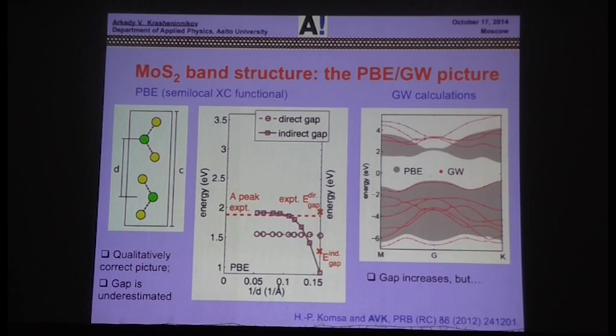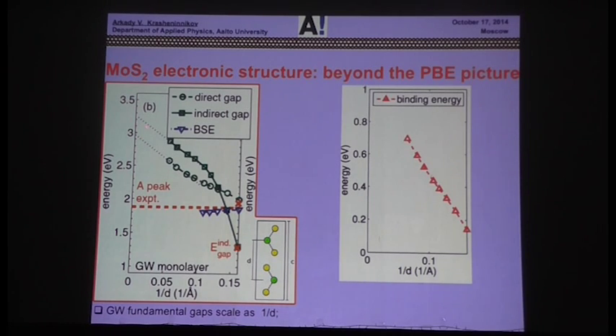But it's also well known that you use GW approximation. It's some sort of post-DFT method to account for correlations and improve on the value of the gap you get. Strangely enough, you get the value of the gap calculated as a function of separation in the layers, which is much larger than the experimental value, which actually gives rise to some confusion. Even some people question the validity of GW approximation for 2D materials.